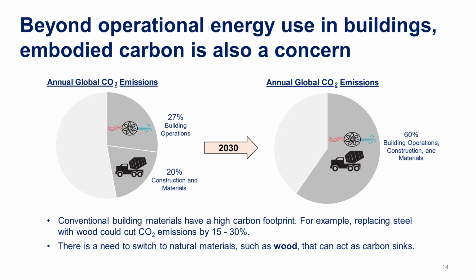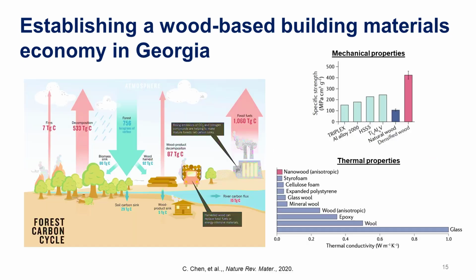So for example, if we replace the steel that's used in construction with wood, we could cut the CO2 emissions by 15 to 30%. And so we really need to be able to switch to natural materials for the building, which can act as carbon sinks rather than carbon sources. And so this gives you an idea of how wood, as a natural material, can sequester a lot of carbon.